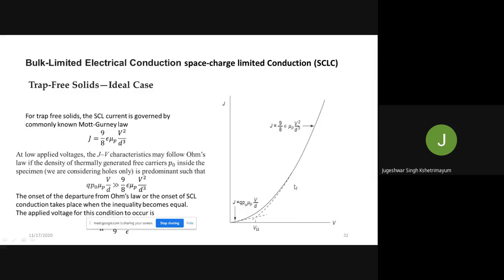For this ohmic contact, during this region, the electrode can be considered as a carrier reservoir that supplies carriers. If the electrode emits more carriers per second than the space charge can accept, the remainder will form a space charge, which creates a field to reduce the rate of carrier emission from the electrode. The current is controlled not by the electron injecting electrode, but by the bulk of the semiconductor or the insulator, in other words, by the carrier mobility inside the material.